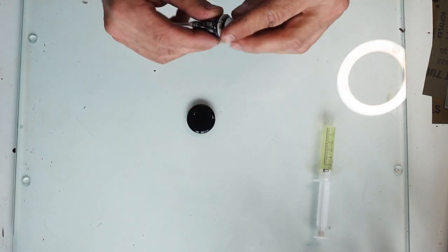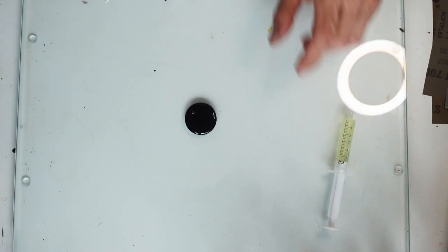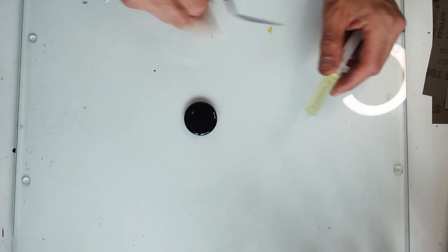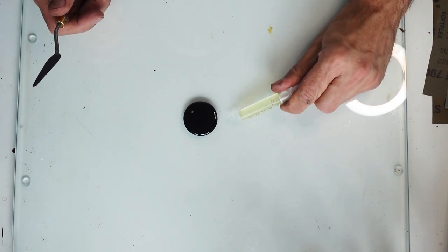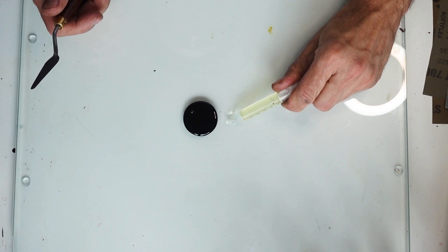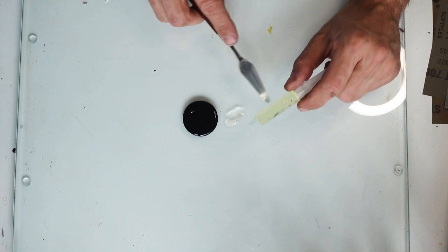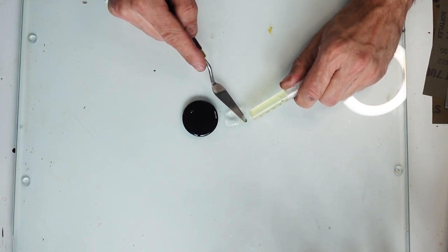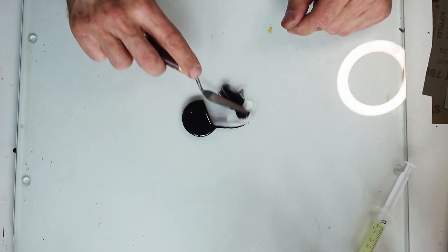Now I will prepare the mixture for Kara-nuri, a very similar mixture is used for many other techniques based on the same principle. So the idea is to thicken the urushi, to make it not drip, not flow, and be more sticky, more viscous, and just thicker. But at the same time, not to let it wrinkle. And so it must not flow and must not wrinkle.